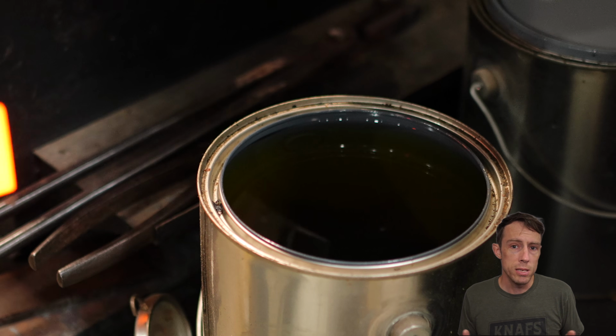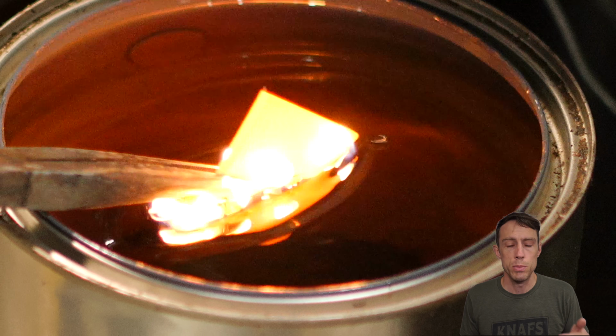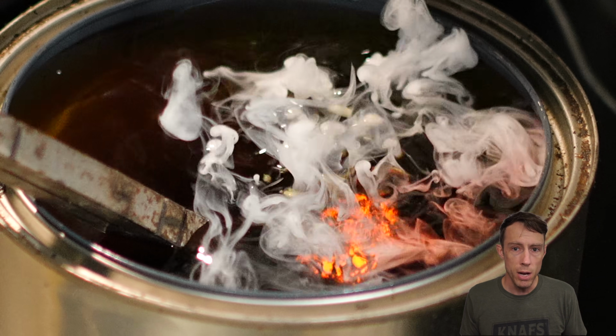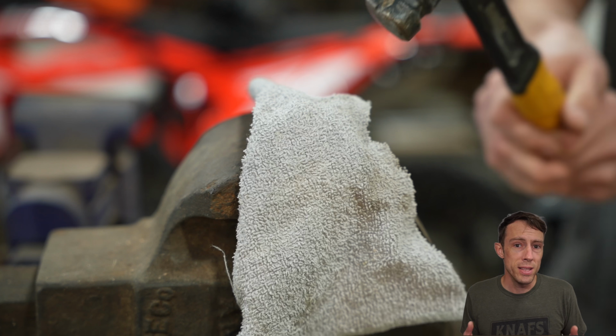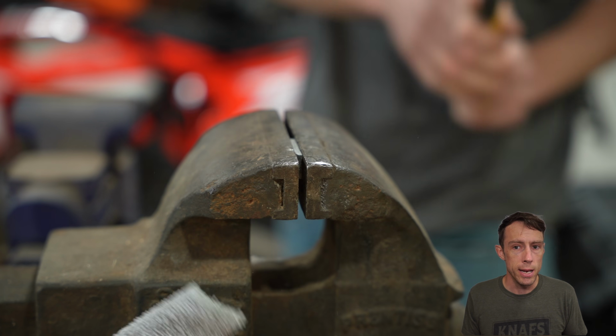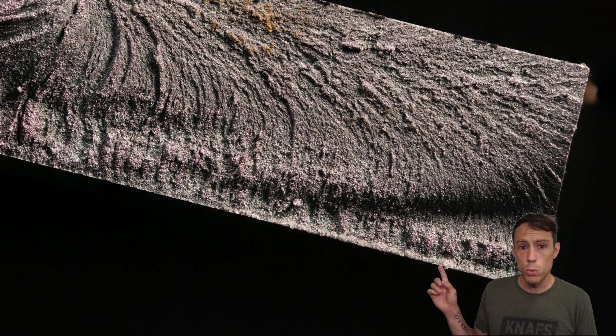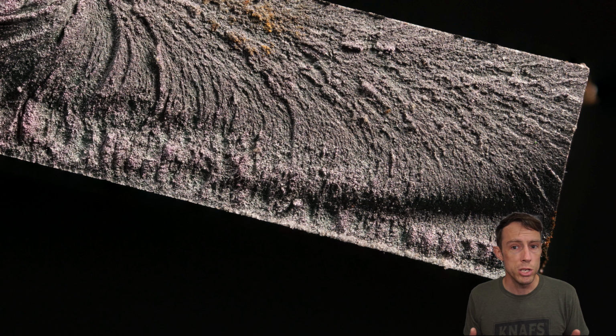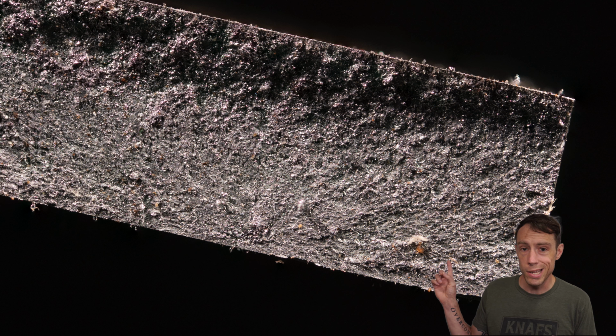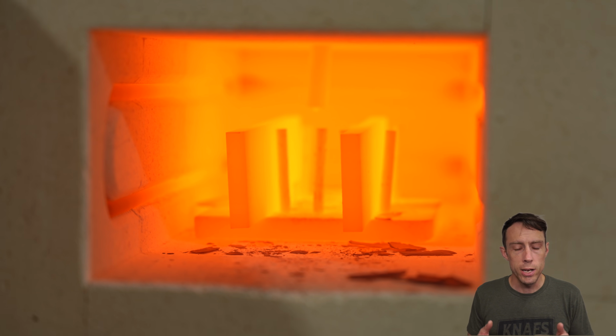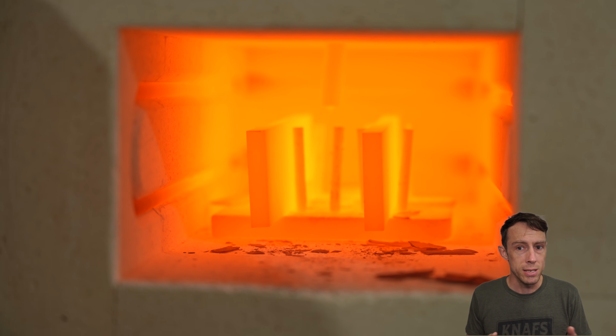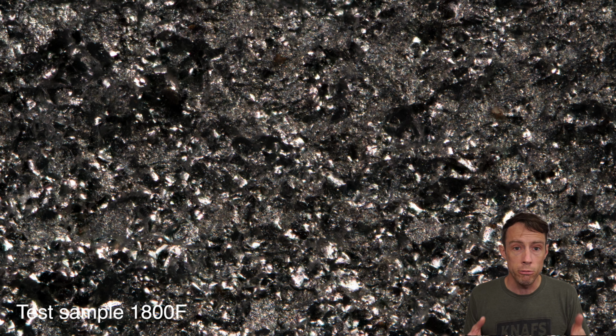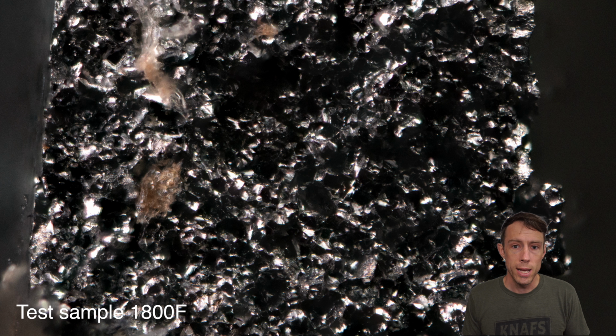Now I also heat treated some test coupons exactly the same as our blade. One at 1475 and one at 1800. I then snapped them in half and looked at the grain. As you can see, the first sample quenched at 1475 has a much finer grain than the one quenched at 1800. This is because the higher temperature, 1800 degrees in 1084, allows significant grain growth within the steel. And larger grain can cause problems.